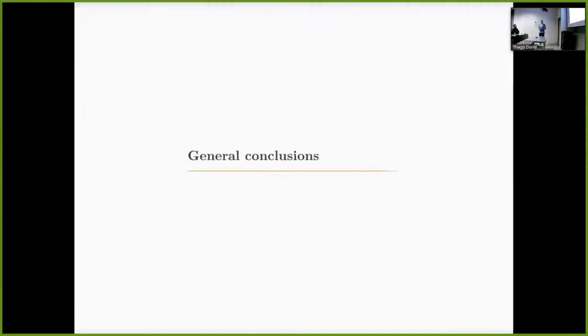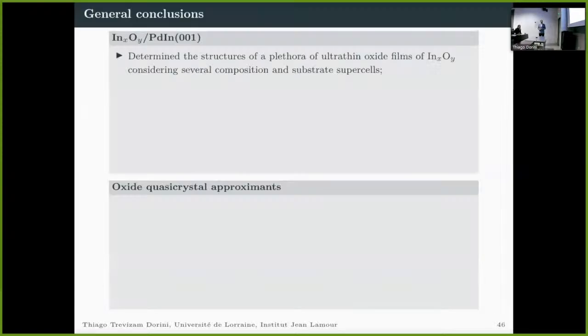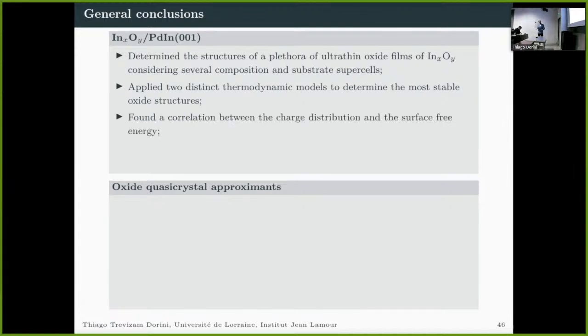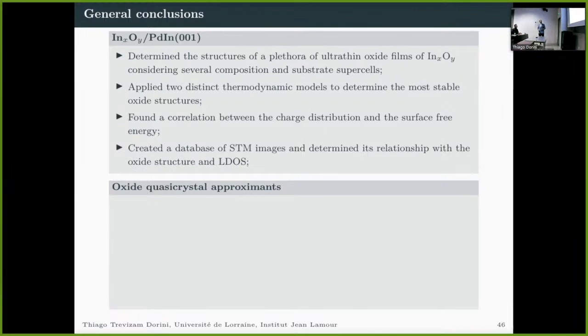Which leads me to some of the general conclusions for this presentation. For this second part, we have determined the structure of a plethora of ultra-thin indium oxide films supported on palladium indium 001 with several composition substrate supercells. We have applied 2 different thermodynamic models to study which were the most stable structures. Between these structures, we have found a correlation between the charge distribution and the surface free energy for these phases. And at the end, we have created a database of STM images, and determined the relationship between the oxide structure and local density of states.